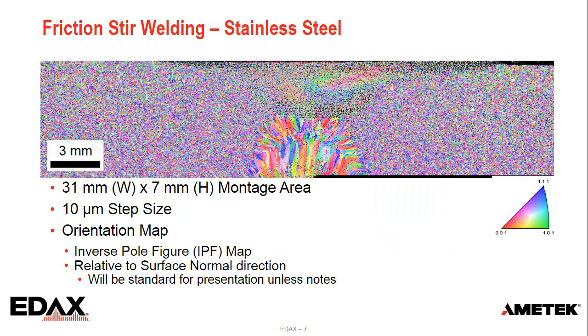So this is an example from a friction stir weld. This is a stainless steel alloy. This is using what we call a montage scan. So it's covering a large area, 31 millimeters by 7 millimeters. Basically we take a field of view, we collect the data, we move the stage, we take another field of view, we repeat that, and when we're done, we stitch them all together to see the microstructure. So this is looking at an area with a 10 micron step size. The map I'm showing here is what we call an orientation map. This is where the colors correspond to the orientation, in this case coming out of the surface normal direction. That will be the standard direction we use in the presentation unless I note otherwise.